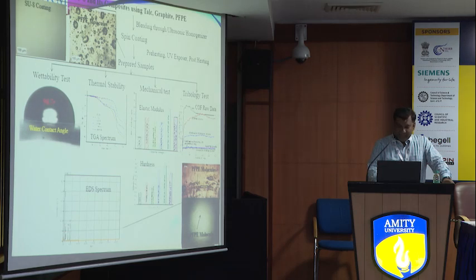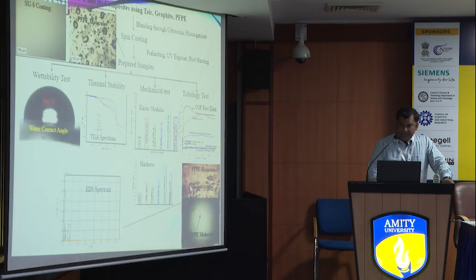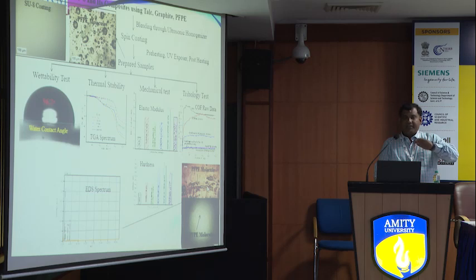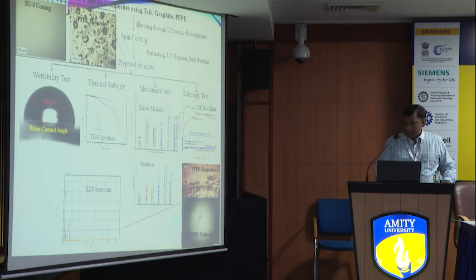And why is that? After adding the filler, you can see clearly here this track where we move. So the layer of the lubricant you can clearly see in that. There is no material displacement, only track displacement. Liquid is displaced from one place to another. And you can also see the liquid on that ball interface clearly. The EDS spectrum also clearly tells that fluorine is transferred to the interface.